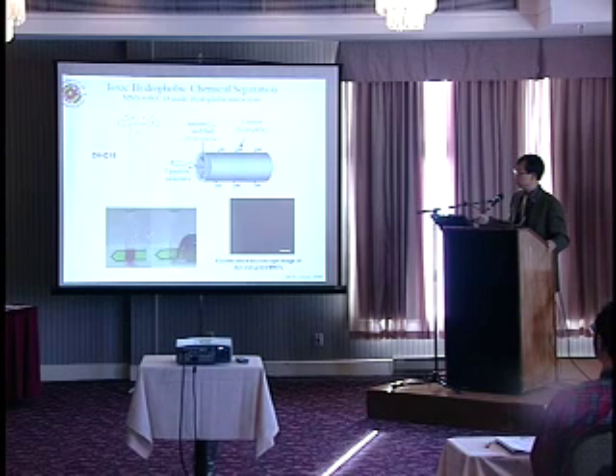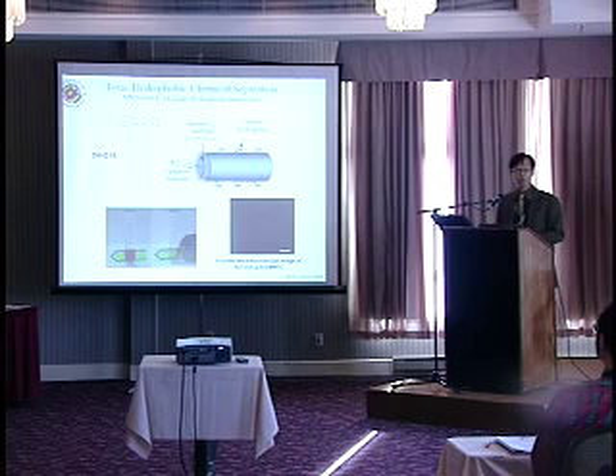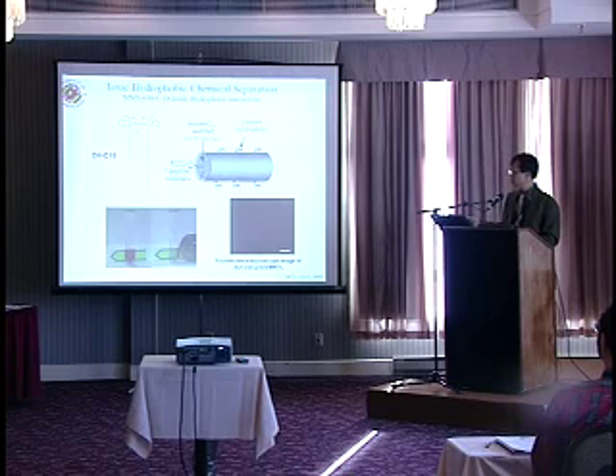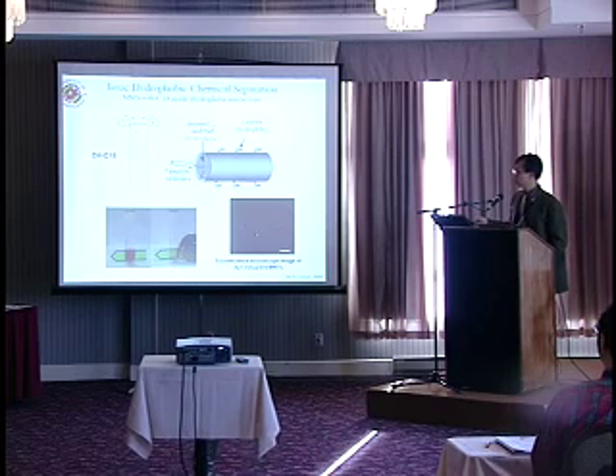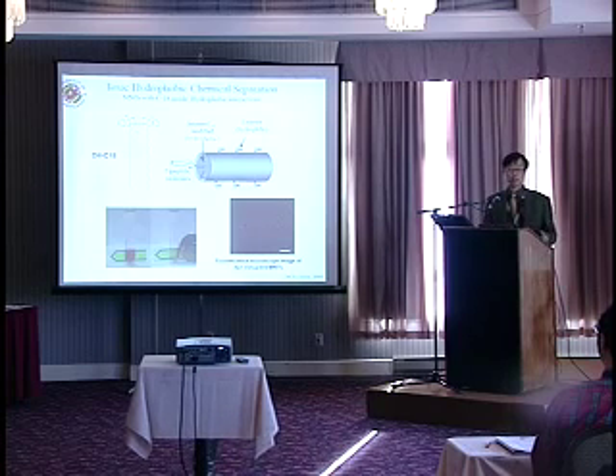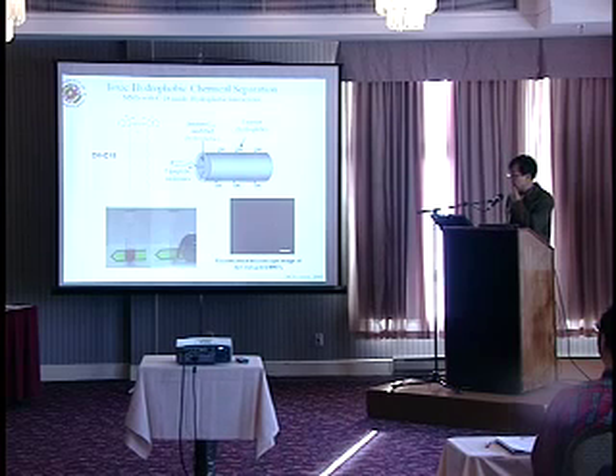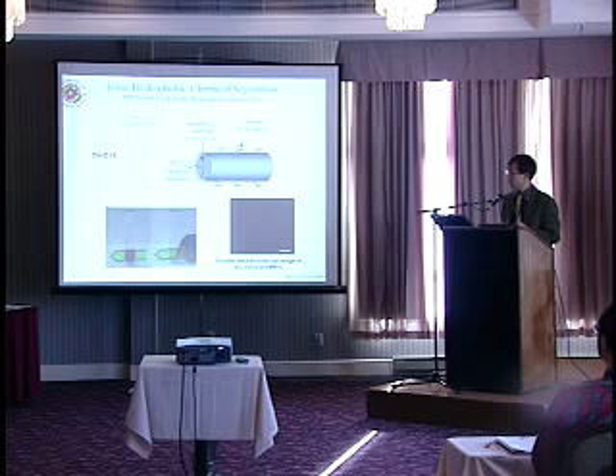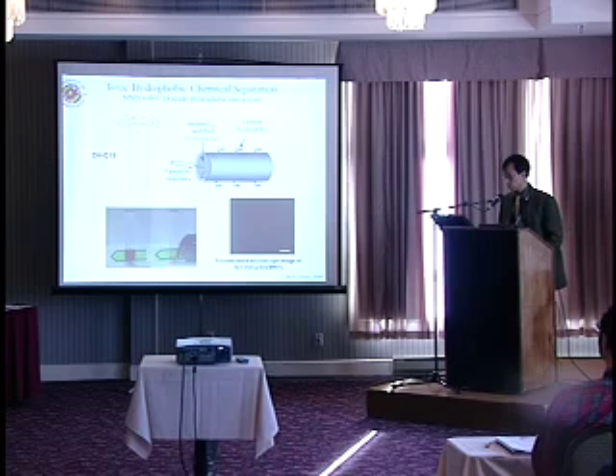And you see this is the aqueous hydrophobic dye solution here. You see red color. And then after putting this magnetic nanotube in here and applying a magnetic field, you see the red color move toward the magnet, which means this red color is no longer from the solution, but from the nanotube. So after simply separating this red color using the magnet, you see individual nanotubes contain a lot of dye molecules inside. So right now, Agilent Technologies is developing a pre-sampler using this technology to get those hydrophobic toxic chemicals.